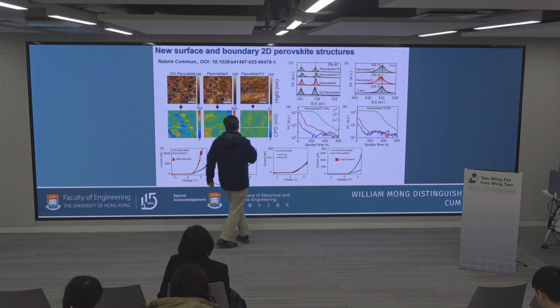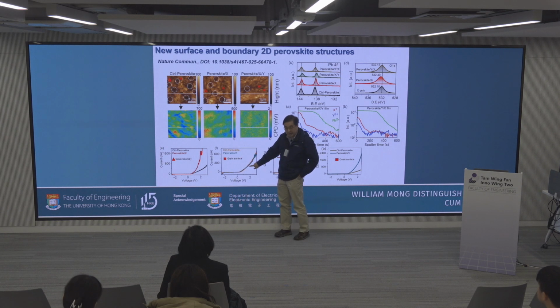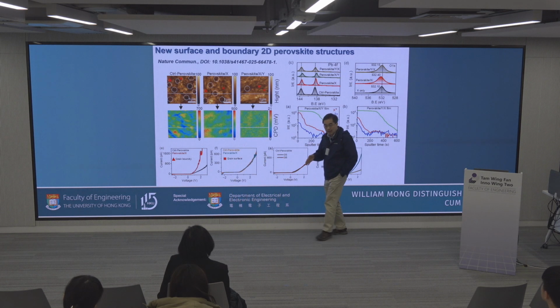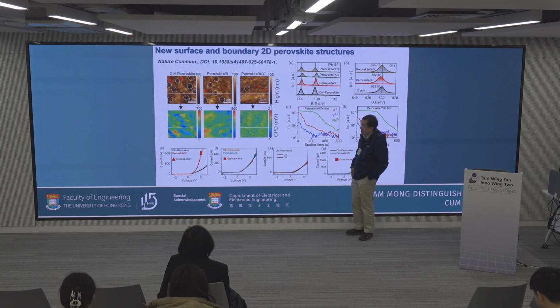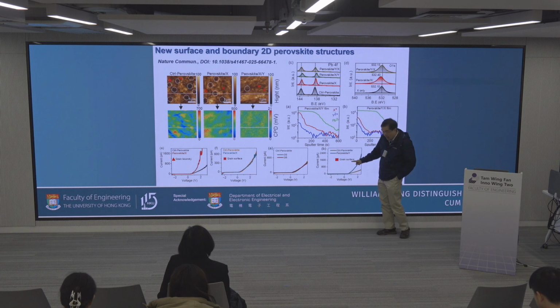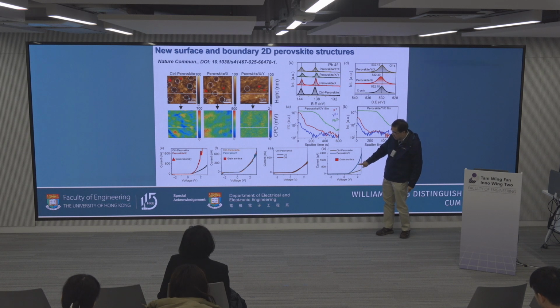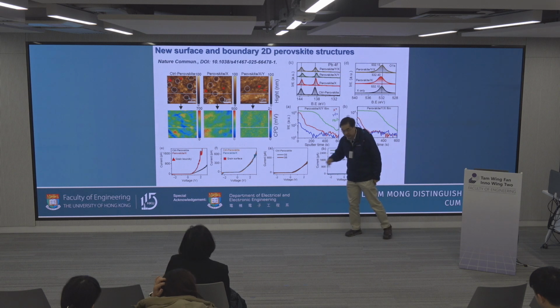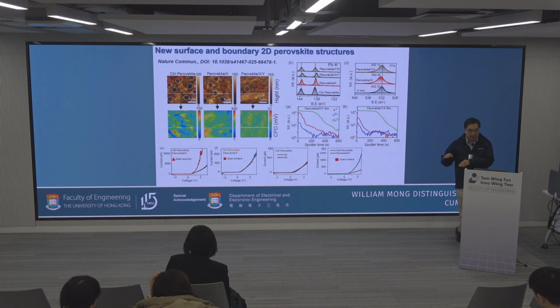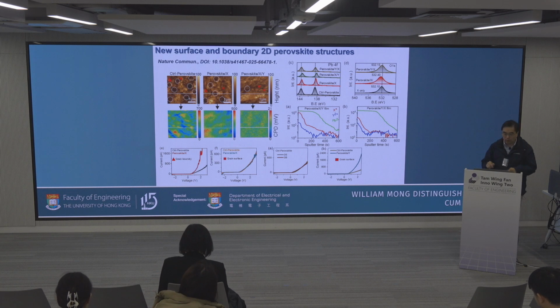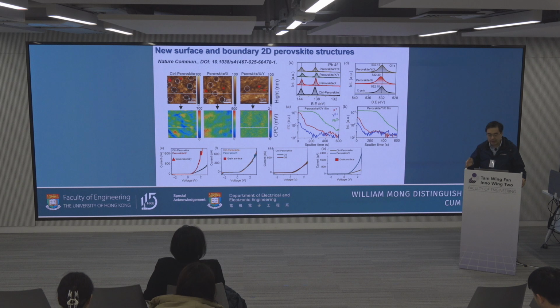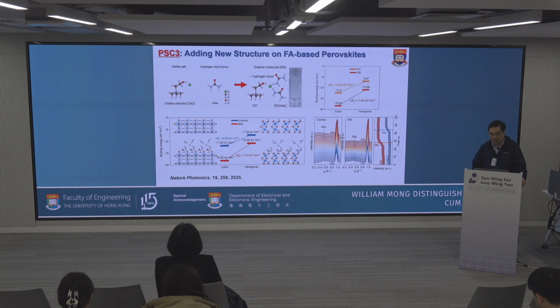How about the surface? If we just have the X ligand, it does not increase the conductivity of the surface. So it means the ligand X does not help with the surface defects. How about the Y? With Y, after boundary modification, we aim for the surface, right? So here, it shows that Y does help the surface, increasing the conductivity of the surface by probing the AFM tip to the surface, and no change over the boundary. So we targetedly make the small molecule form the 2D material at the targeted location, helping us to address the boundary and surface defects, suppressing the device degradation.